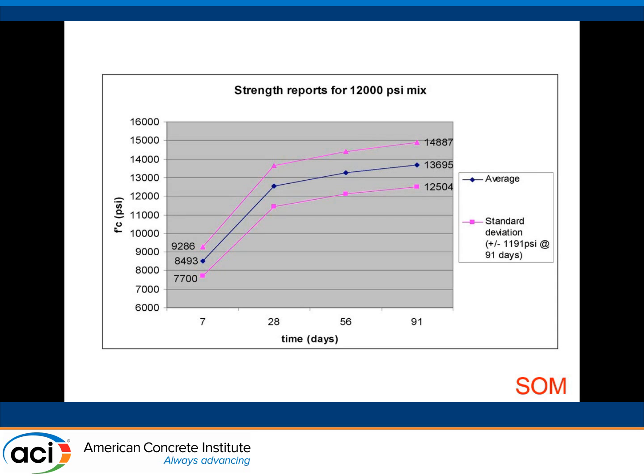Some data of the strength reports for the 12,000 psi mix. We were testing out at about upwards of 13,500 or so for the average strength at about 90 days.